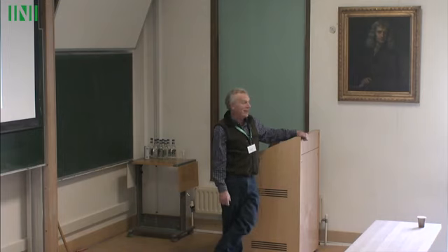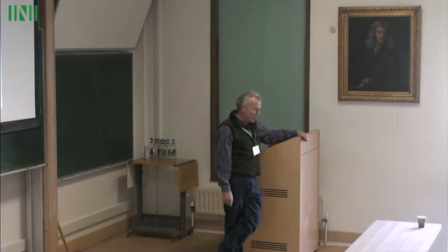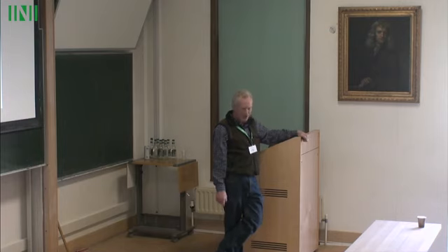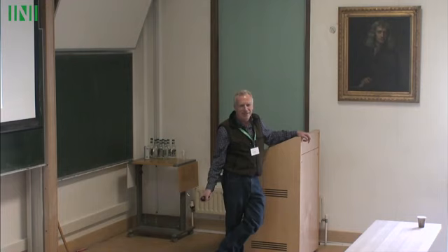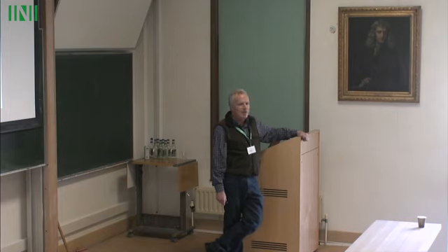No, I don't know. What's really needed for the energy conversion is just being able to have every cycle the same. The transformation temperature, you don't want to migrate, and you want repeatability. You want not part of the specimen to die after cycle 1 million, and so it's really the reversibility, repeatability of the material that's needed. I don't know whether there would be any interesting implications beyond just general scientific interest in this non-repeatability. Yeah, it was very surprising to us.